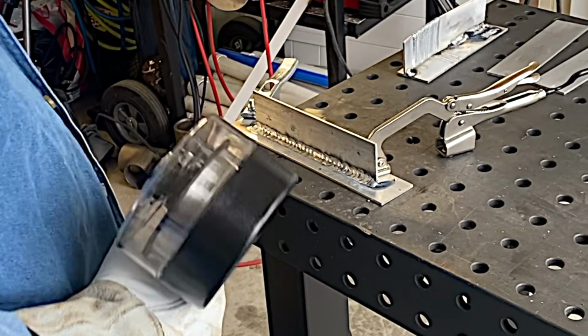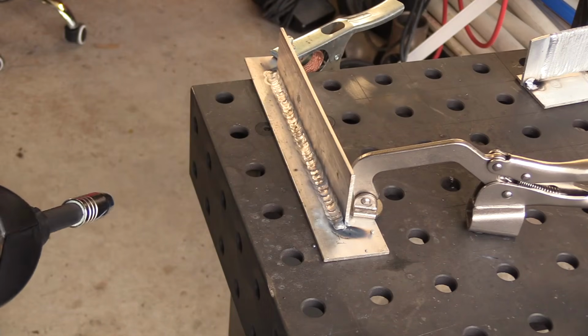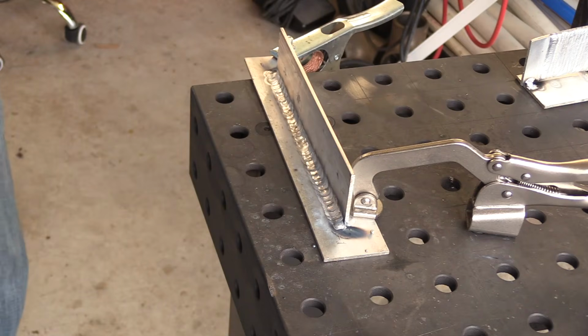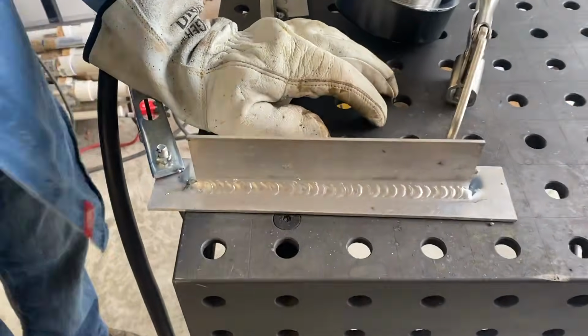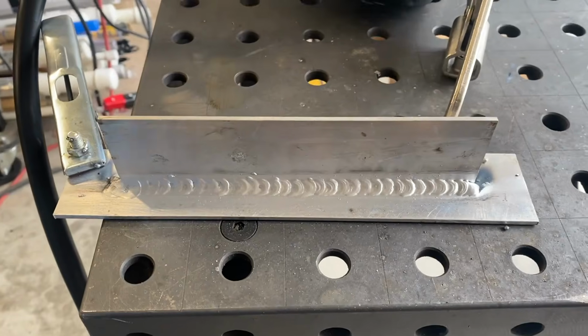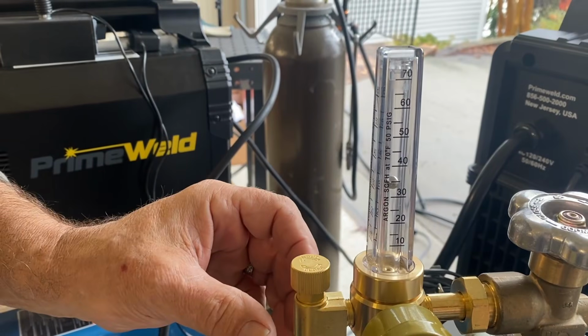For this setup, 35 to 40 CFH was close. Wasn't perfect, got a little bit of soot, especially on the start, but somewhere around 35 to 40 CFH was close. The way argon flow makes a difference is if you don't have enough, you're going to get soot, because of that cleaning action from the reverse polarity. It's kind of like TIG. You get a cleaning action outside the bead, but you won't get that if you don't have enough argon. So you'll get a sooty weld and a dirtier weld.